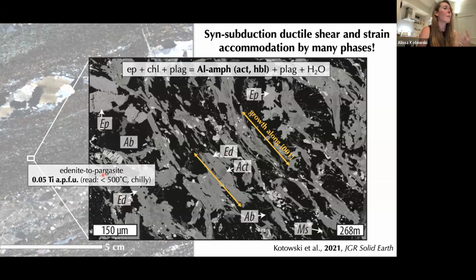If we do the same thing with the titanium content in these minerals, we now have much, much less titanium, so 0.05 atoms per formula unit. So this puts the formation of this prograde subduction fabric at a maximum temperature of 500 degrees Celsius. So these prograde fabrics demonstrate that many phases are here and acting to accommodate strain together. So for example, we have amphibole, epidote, and albite. So now we can take a closer look at this with EBSD as well to think about the deformation mechanisms.